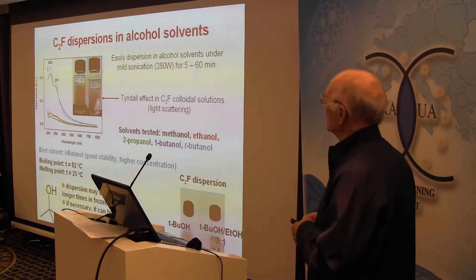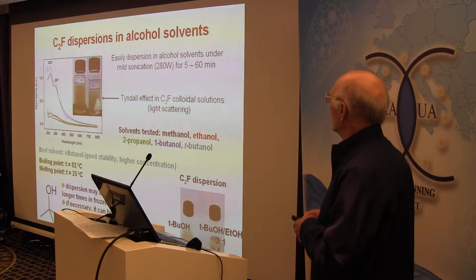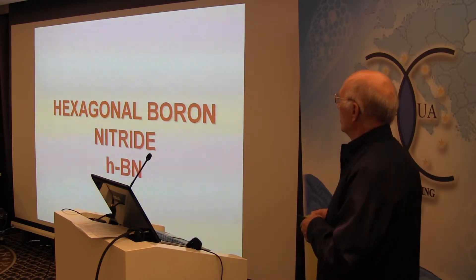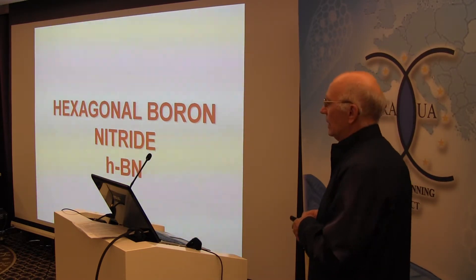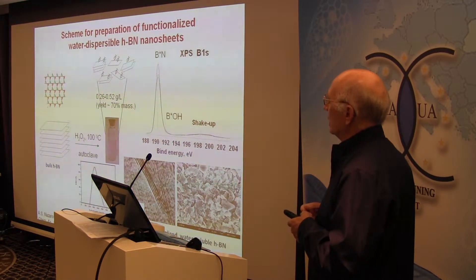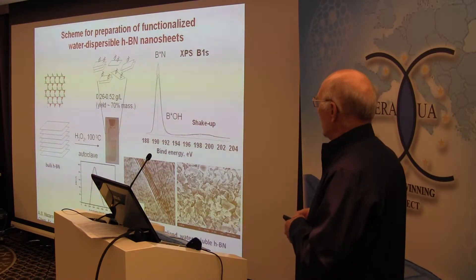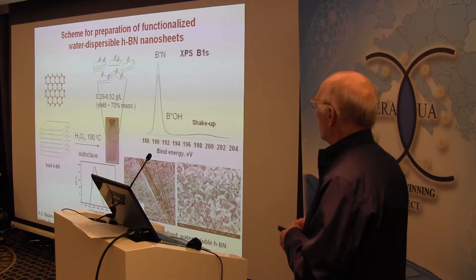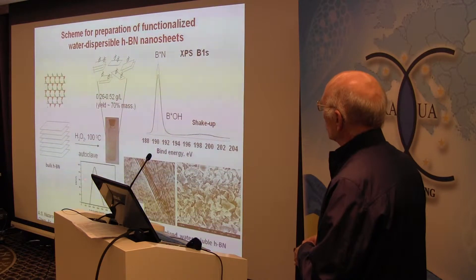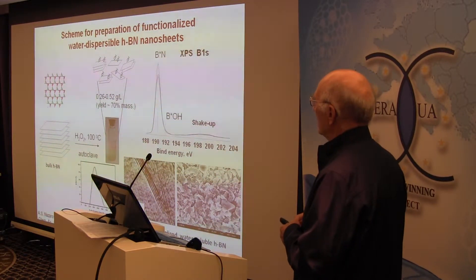You can see different modified materials using our high exfoliated graphite. Several words about boron nitride, which has a related structure. We used an analogous procedure for exfoliation — an autoclave procedure using hydrogen peroxide — and in this procedure we prepared good fine particles with a diameter of about several hundred nanometers.